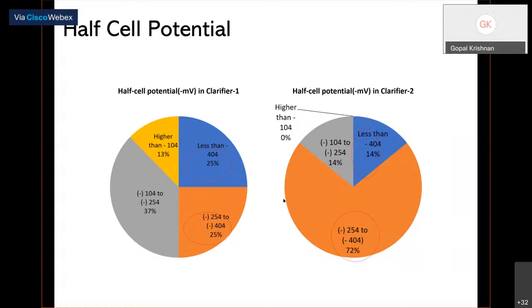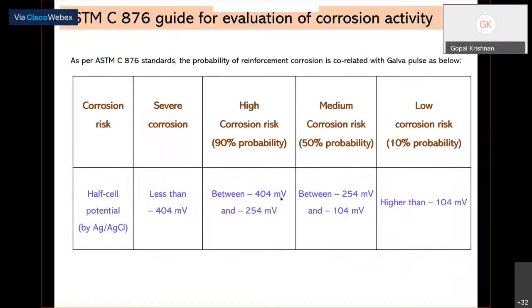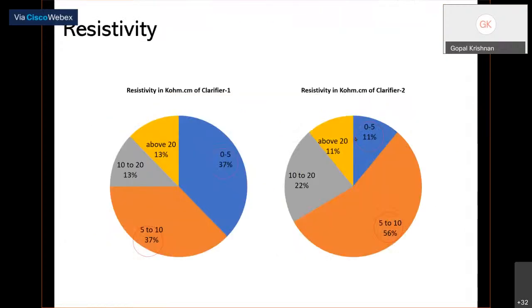So overall, the corrosion activity is happening because of the continuous leakages happening in the structure. So we have to take effective action immediately. See, high to severe, I said, minus 254 to minus 404 millivolt by silver chloride when we measure. This is as per ASTM C876 specification. Even the resistivity gives very negative values. It is also showing that the probability is higher.